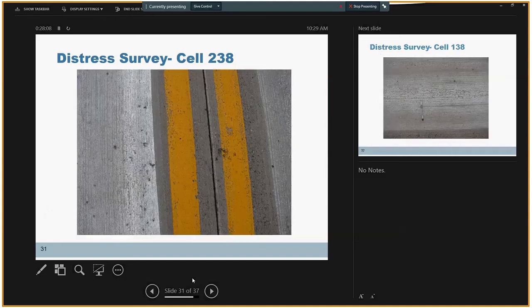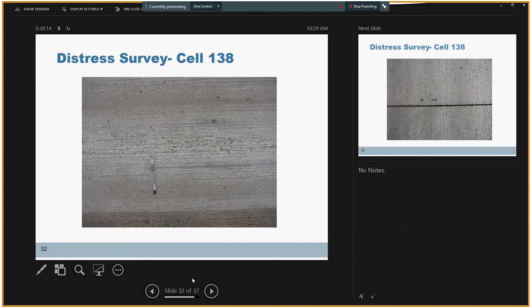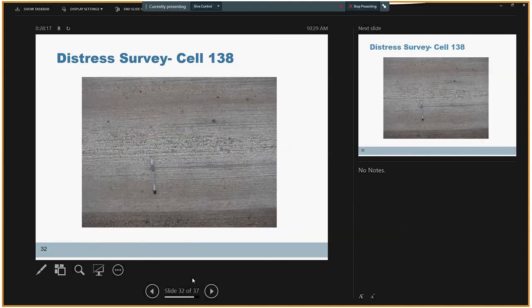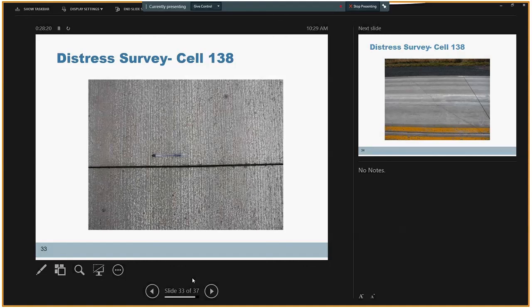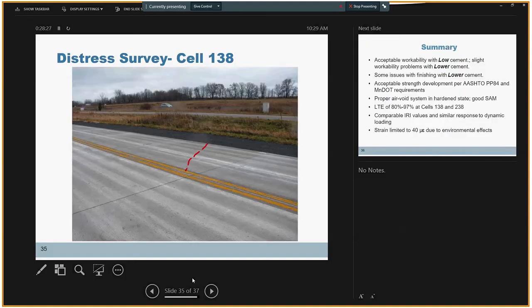And some slight problems with finishing the surface in concrete with lower cementitious material content, which was kind of expected based on the workability data, but not such a problem in concrete with higher cementitious material. Excellent surface texture and excellent performance after 1 year. And the only problem we had here in cell 138 with low cement was kind of a diagonal crack in one of the cells exposed to traffic loading, which I think is something structural because of the loading, not the material properties here.